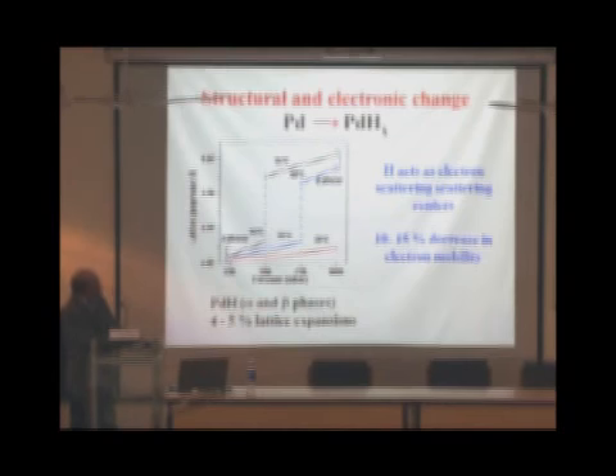And so there is a 10 to 15% decrease in the electronic mobility, and the other effect which takes place is the change in the lattice parameters. The expansion of the material takes place. So you go from this, the palladium lattice constant. As you start putting hydrogen, at low concentration of hydrogen, you have the alpha phase. Then as the concentration of hydrogen increases, you have a beta phase. So when you go from alpha phase to beta phase, there is some sort of a 4% expansion in the lattice. And that is the reason that you require that void. If the void is not present, if the topography is very compact, the palladium nanoparticles cannot expand, hydrogen cannot go inside, and it cannot come out also the same way.